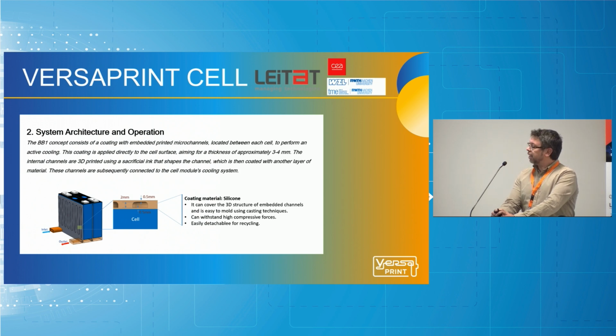These internal channels are 3D printed using a sacrificial ink. The shape of the channel can be easily adapted by 3D printing, and is embedded within these 2 layers of this material. This coating material was a challenge to select, and finally it was decided to use one kind of silicone that is easy to mold by casting techniques to achieve the geometry we want for the coating, and can withstand high compressive forces, and can be easily detachable to ease the recycling. All these channels are later connected to the cell module.